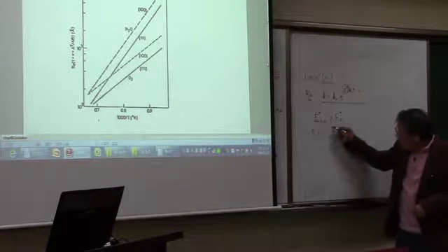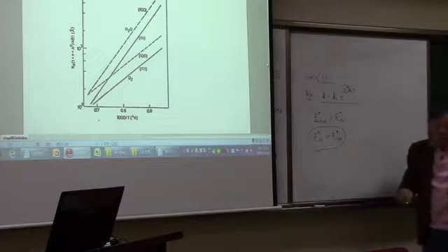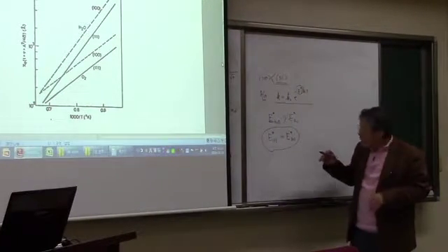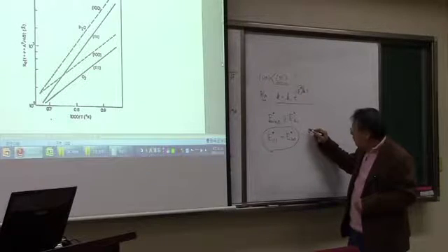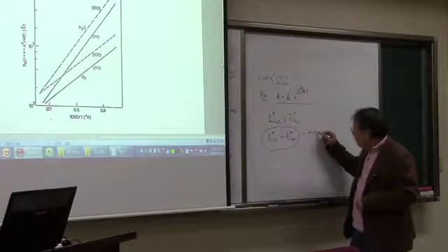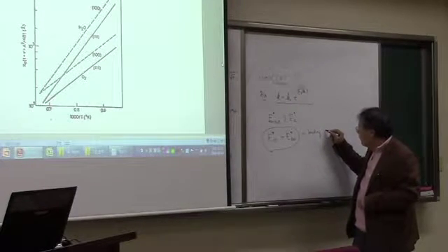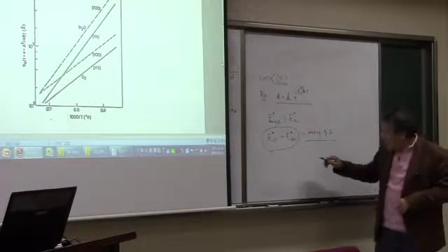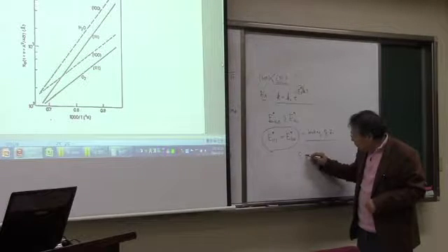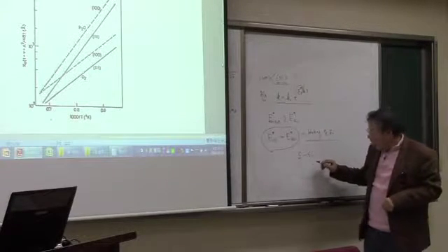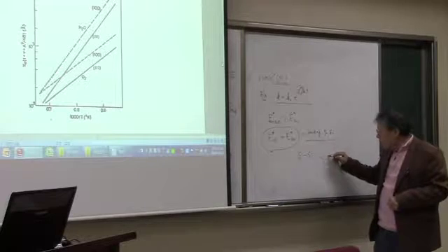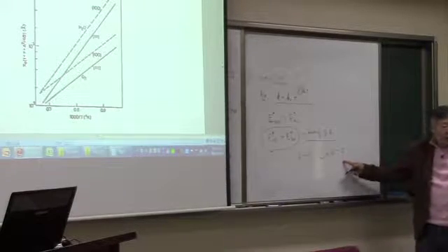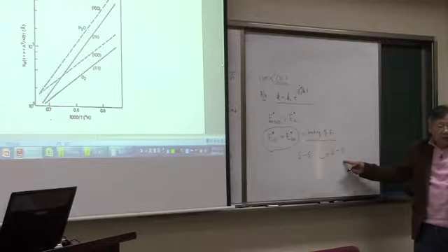And the reason for this is that the oxidation is related to the bonding energy of silicon. Okay? Actually, what it does is you break the silicon-silicon bonding, and then you're going to have a new bonding with the oxygen. That's what the oxidation is, right?